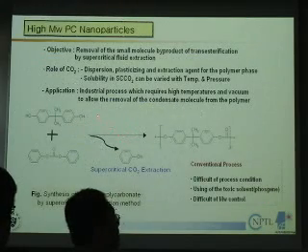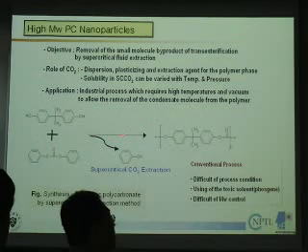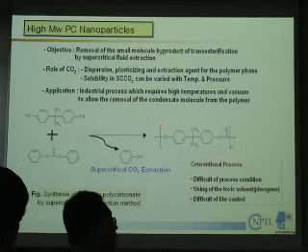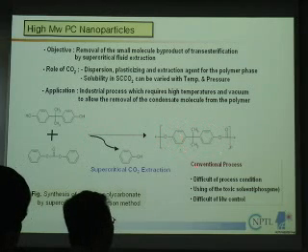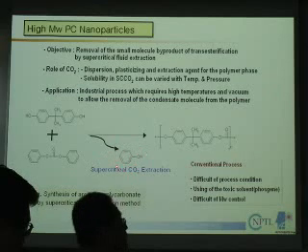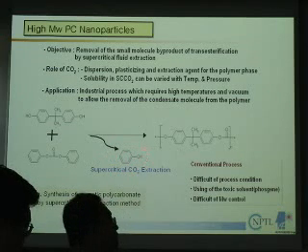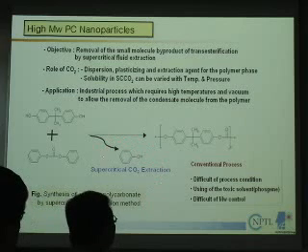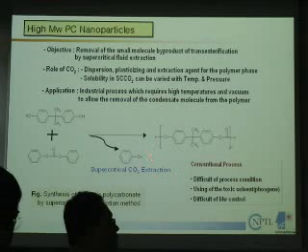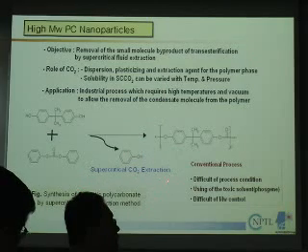Okay, if you remember my first part of the presentation, we chose this polycarbonate system to make nano-size polycarbonate with high molecular weight, because during the reaction it makes phenol as a side product. So whether you can actually extract this phenol from the growing particles will determine whether you can make high molecular weight polycarbonate particles in the end.